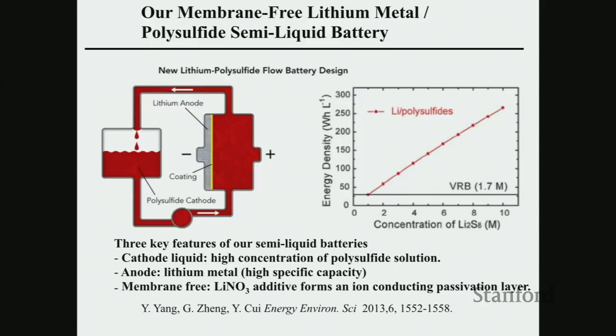A number of years ago, we showed lithium polysulfide has much higher solubility, and compared to vanadium, that's 1.7 molar, and lithium polysulfide can have even 5x more. So you increase the amount of energy you store, you reduce the cost. And we invented this technology with a metallic lithium anode. So you have a solid, you have a liquid. They react by themselves, forming this self-decomposition compound, the SEI. That's your membrane. So you don't have to use other membrane. You reduce the cost. These still remain as a very attractive idea of a semi-flow battery for the grid-scale storage.